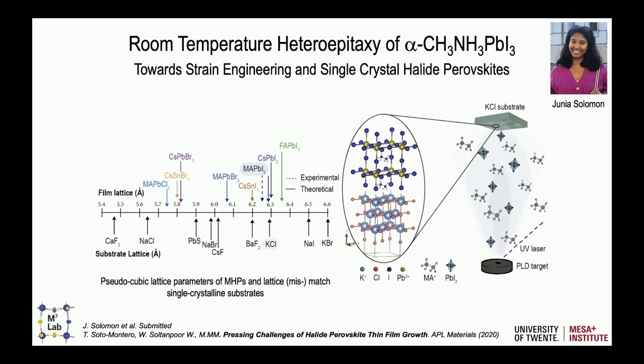So to start, I would like to start with the heteroepitaxy of hybrid halide perovskites. So the idea of epitaxy is to really get to the point where you can do strain engineering of these materials and also single crystal halide perovskites. So we want to get to the ultimate case where you have a thin film that is epitaxial, and basically you have very little defects, and you can understand the fundamental properties of the material. So to do epitaxy, what you look at is what kind of substrates you can use that will have the same lattice match as your halide perovskite.